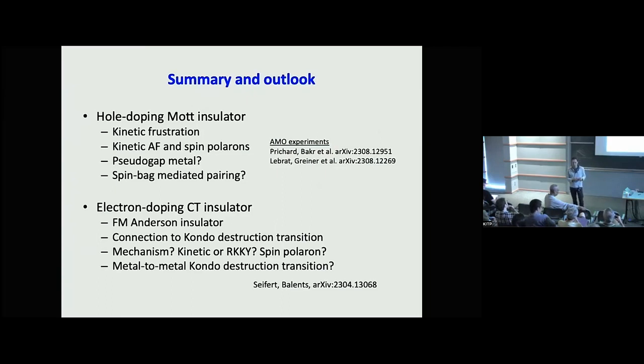As Achim's asking, if I could ask a reverse question: I look in a regime of the phase diagram where the system wants to be paramagnetic, but I excite it with circularly polarized light, and I create an imbalance, a lot of K valley electrons. How do they get back to the K prime valley? It's actually the excitons, and it's the exchange interaction of the excitons in the two valleys that causes the valley relaxation. That is, as far as we know, for a single layer TMD, the dominant channel that relaxes the valley if you pump by circularly polarized light.